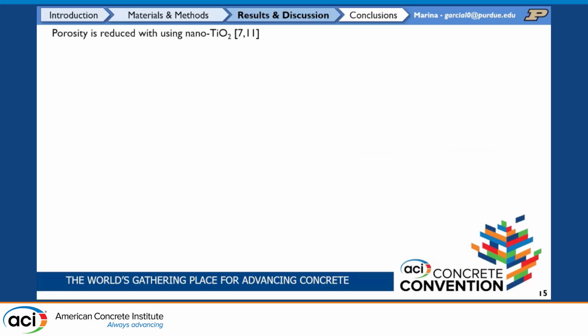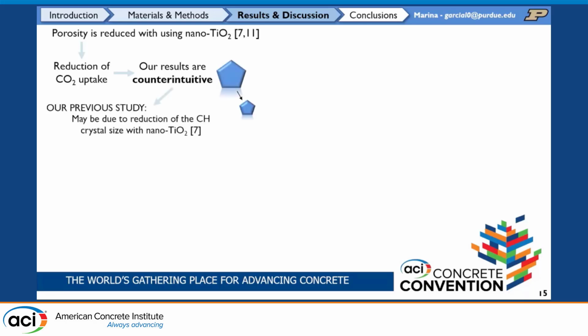We do know that porosity is reduced when we add titanium dioxide nanoparticles. So this should result in a reduction of the CO2 uptake because we're reducing the diffusion of CO2 into the pore structure. However, we're getting the opposite results, right? We're having counterintuitive results. In one of our previous studies, we saw that this may be due to the reduction of the crystal size of the CH. However, is there any other mechanism that's contributing to this?